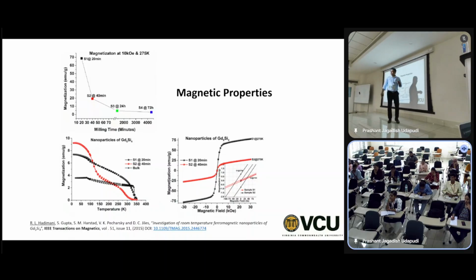It is by adding some media called milling media. It basically distributes the energy, and then you get smaller particles, but you get higher or similar magnetization. So here, if you look at these different size-separated particles, they have different transition temperatures. That means if the particle size changes, their property also changes. So that's why you need to retain or size-separate the particles.